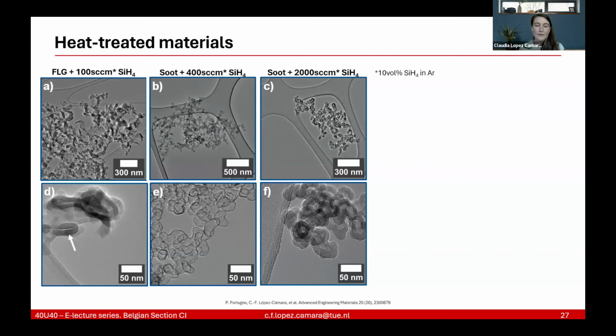We took it off. Therefore, what happens is that the silica kept the inside of the silica in the shape of the graphene. So we created hollow nanoparticles of silica with the inside in the shape of a graphene. And perhaps it's easier to see in the other 2 examples. In those, instead of graphene, we use soot, because we wanted to see if we can do it with graphene, can we change the shape of the initial carbon material and cover it again with silica and then burn the inside, getting rid of it in the oven, creating shell structures. And we could actually.